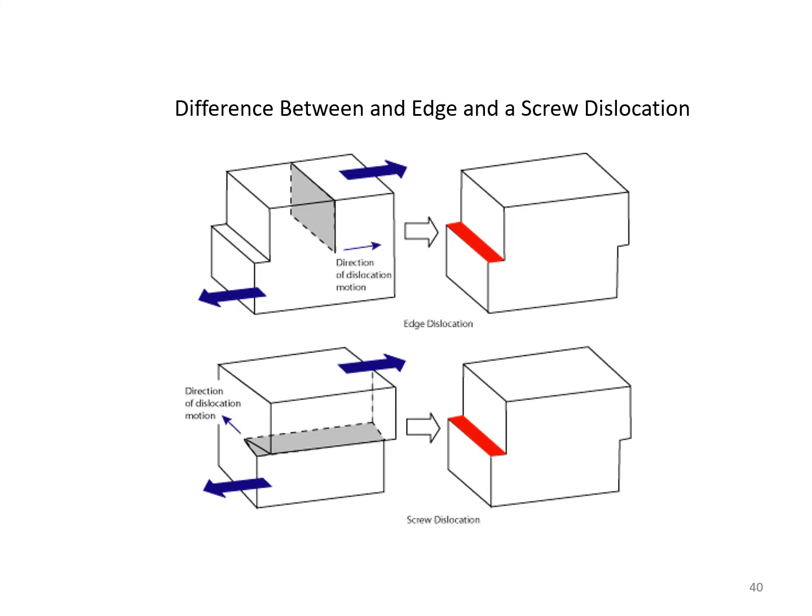So the directional motion of this dislocation is one direction, but the net shear, like tearing a telephone book, is at right angles to this, in the direction of the Burgers vector. So a screw dislocation has a Burgers vector along the line of the dislocation, but the direction of motion is perpendicular to both. For an edge dislocation, the Burgers vector is perpendicular to the line of the dislocation, but in the direction of motion of the dislocation. They both give the same shear, but they are two types of dislocations.